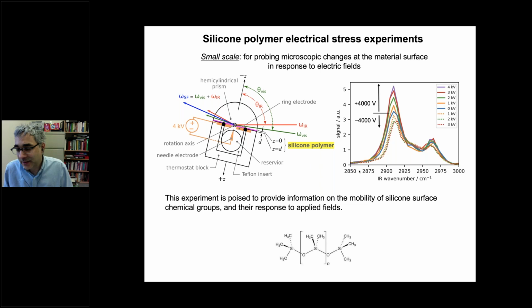Another thing that's really interesting, if you look at the chemical structure of the silicon rubbers, the silicon-oxygen bond is the most polar part of the molecule. So this is what really is expected to move with respect to the electric field. And yet what we're probing is the silicon-methyl group, because that's the part that is imparting hydrophobicity to the material. So it's almost like the silicon-oxygen bonds move in response to the field, and the methyl groups are along for the ride. And so this is very interesting to understand the relationship between these.